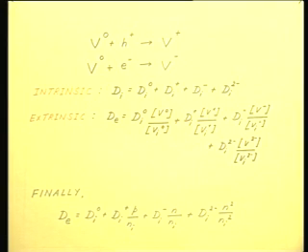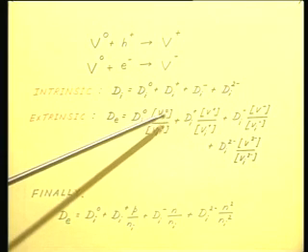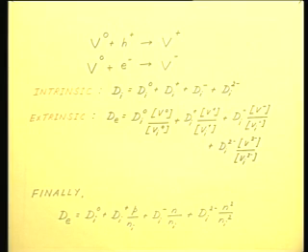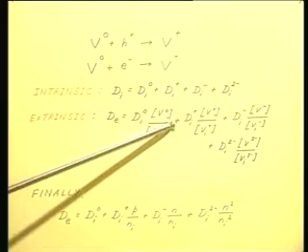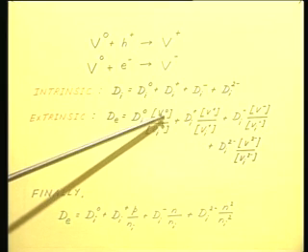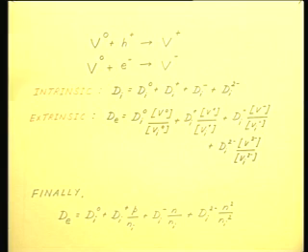And now if I combine this with these expressions, that is, the relative concentration of the vacancies in various charge states between the extrinsic and intrinsic case, then what is the ratio of the concentration of neutral vacancies in intrinsic and extrinsic case? The ratio is 1, as I told you, because the number of neutral vacancies is only going to depend on the temperature, not on anything else. So, this term becomes 1, simply I get dE, the first term is di0.